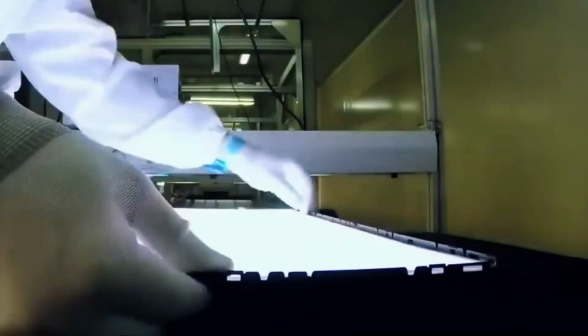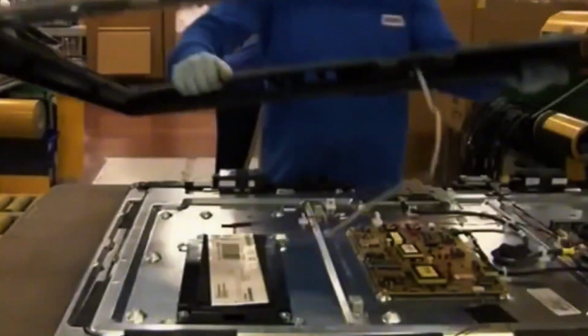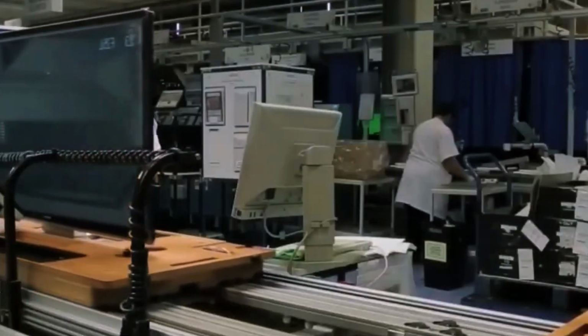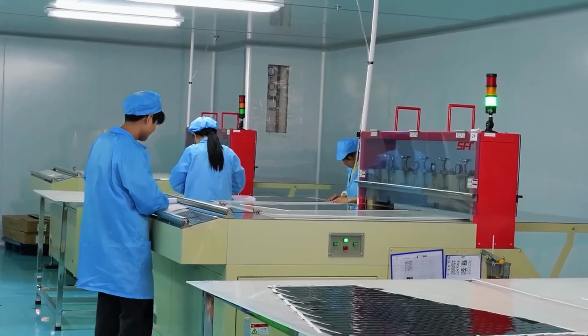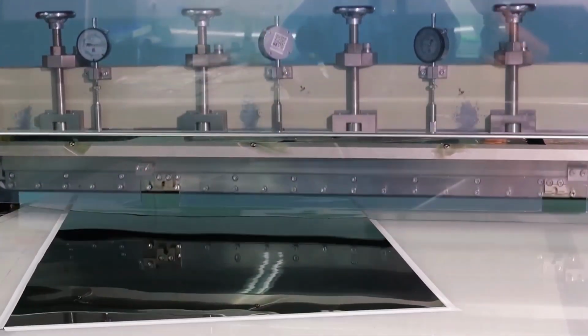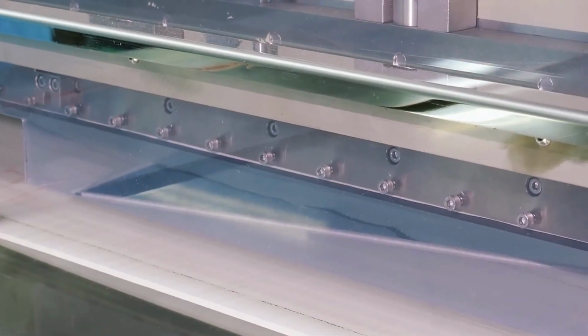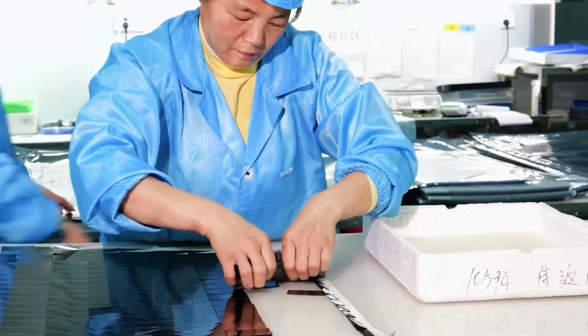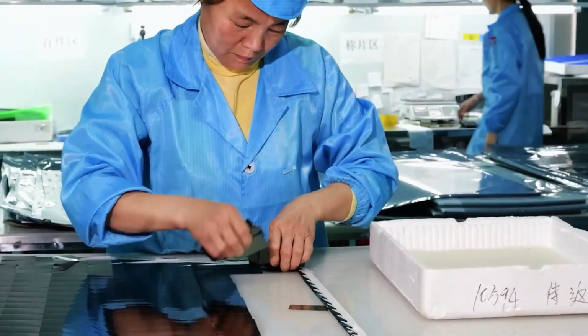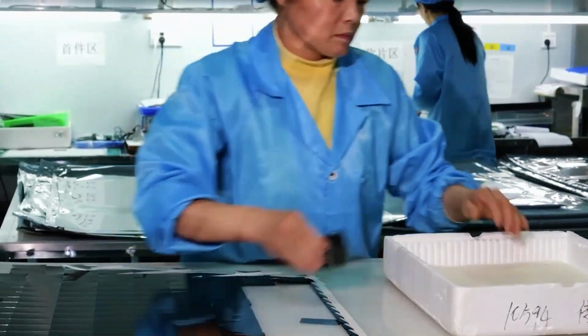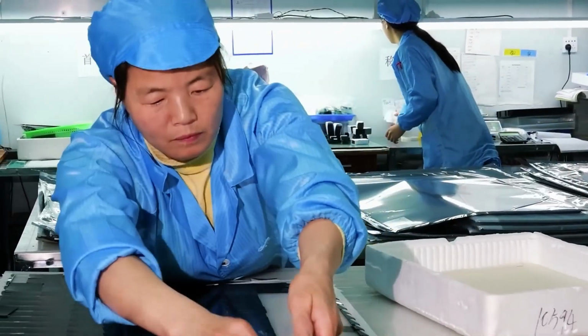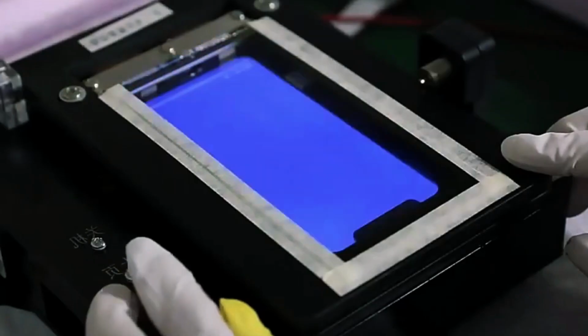Finally, the panels are cut and tested. Mother panels are laser cut into sizes from 5 to 7 inches, producing up to 100 screens per sheet. They are subjected to drop tests, pressure tests, and flex tests simulating real-world use. Brightness, power consumption, and viewing angles are measured. All of this ensures AMOLEDs last as long as possible, although their optimal lifespan is typically 2 to 3 years compared to about 7 for LCDs.